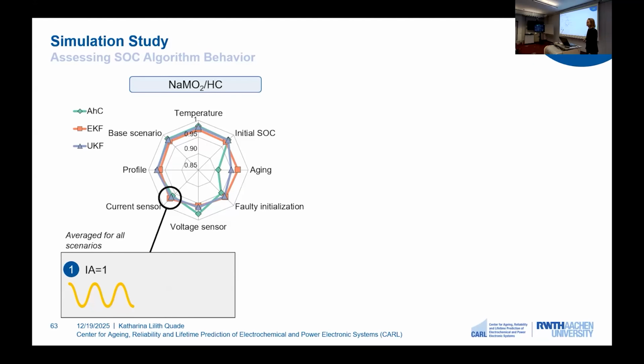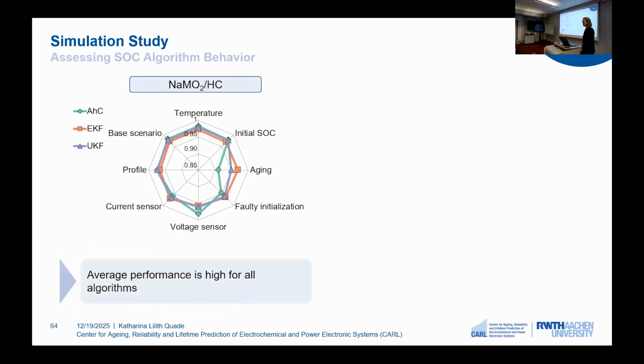And let me explain the extrema. The index of agreement equals 1 when our estimated trajectory is a perfect match to our reference trajectory. And the other extremum is when our index of agreement equals 0. And this happens when our estimation trajectory is the complete inverse of our reference trajectory. So let's return to our spider plot. In general, we can see that the average performance is high for all algorithms because in nearly all conditions, we have a very high index of agreement value, so close to 1, which is quite favorable.